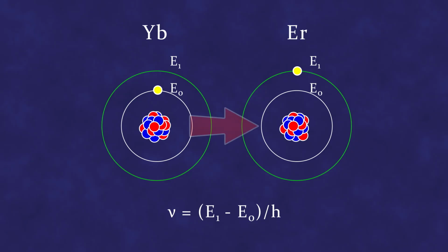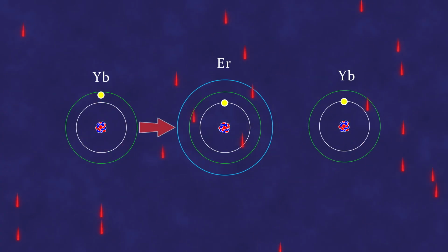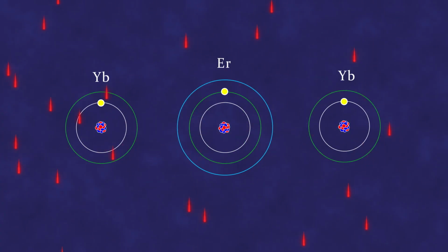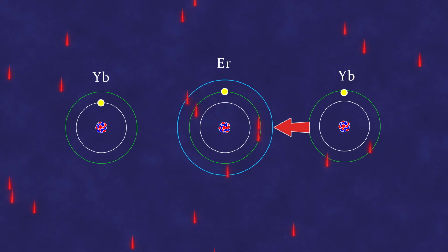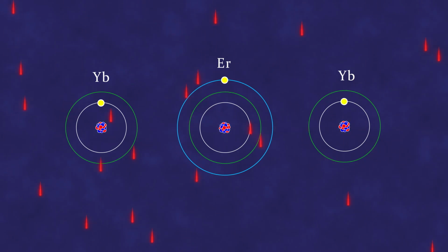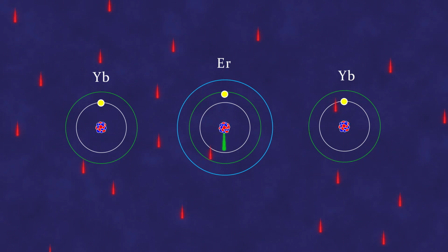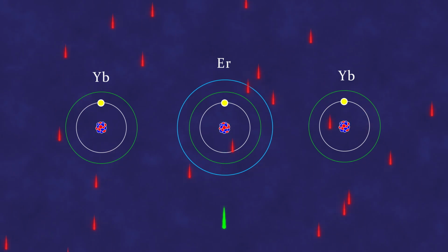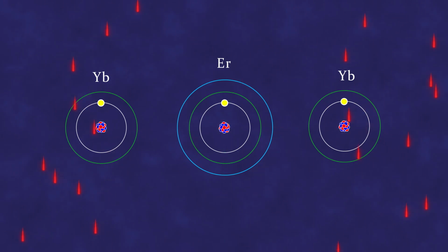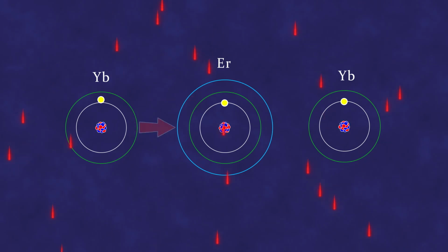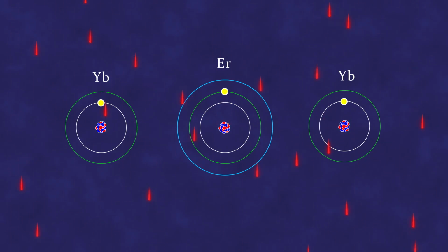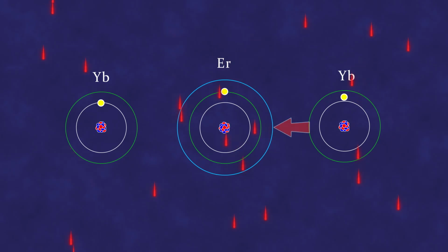That is the Förster transfer, and it is precisely thanks to it that the ytterbium-erbium pair, having matching transitions, can be used to upconvert infrared radiation into visible light. So, if we place a material containing erbium and ytterbium atoms in the path of an infrared radiation stream, upconversion can already begin on its own. The only essential condition is that the distance between the ytterbium and erbium atoms should be small enough, ideally around 1 nanometer. And indeed, it will start.